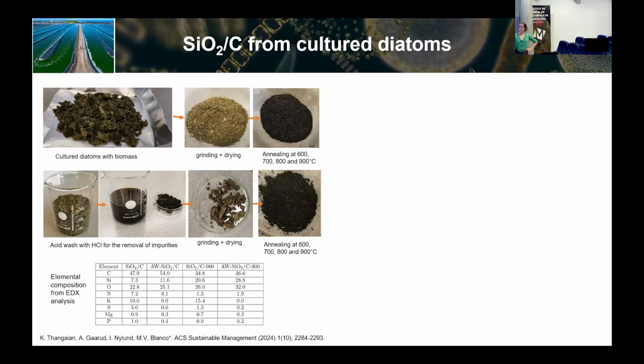So if we look at the EDX results, we can see that for the material that was non-washed, we have high amounts of impurities. Potassium may be the most important one, also nitrogen. When we do the acid wash, we just get rid of most of them. And even in the annealed material, with the acid wash, we almost have nothing of potassium, but in the non-acid wash, we have quite significant amounts of potassium. We don't know yet still where this potassium is, but it is there.